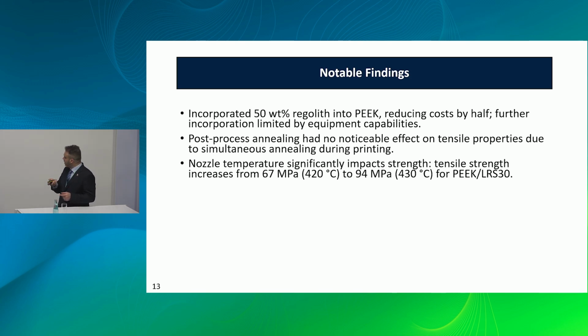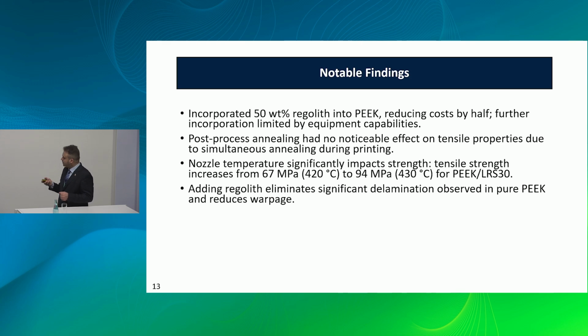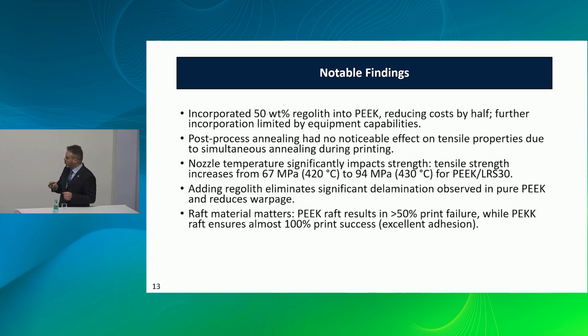lunar regolith, 30%. And adding regolith eliminates significant delamination between the layers of pure PEEK and reduces warpage as well. And raft material matters for this printing. For PEEK, we had more than 50% print failure, but for PEKK raft, as it offers excellent adhesion to the PEEK, we can achieve almost 100% print success.